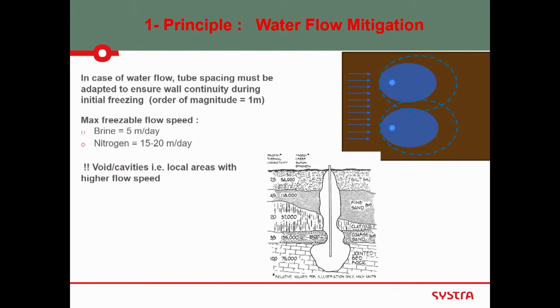And as we said, if the flow of water is too fast, the water cannot go from liquid to solid. And what is the actual velocity where you don't need to do something? If you use brine, in fact, it's 5 meters per day. So if the flow has a speed which is more than 5 meters per day, you cannot use brine. You will not be able to freeze the soil. So you have to reduce the permeability or use nitrogen, because the limit is between 15 and 20 meters per day. If it goes even faster, either you can grout to decrease, in fact, the velocity, or do something else. But it won't work. And as we said before, cavity is kind of important in the technique. If you get cavity, either you fill it, or you don't use ground freezing.